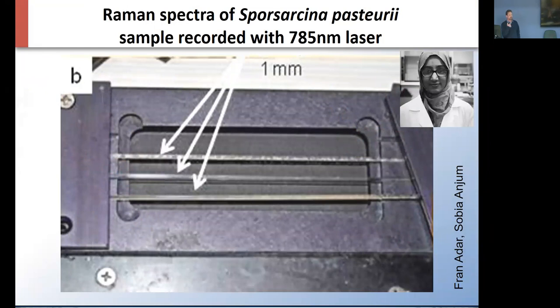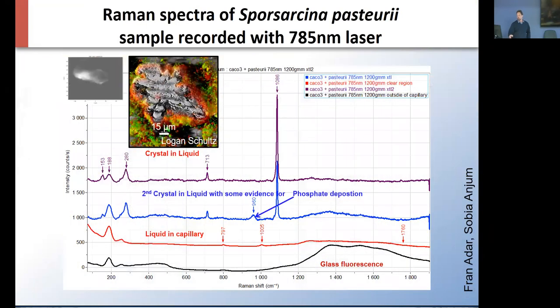So again, going back to what would happen in a flow system where we want to plug something, we use these capillaries, and Sobia, one of my PhD students, has worked with Fran Adar to basically, again, take these capillaries, and it's the same principle as I already explained in my previous slide with struvite. But what you see here is in the confocal, we can again image cells, red and green, as well as the crystal, but we don't know what it is. With the Raman scope, we can then go in and actually look at a crystal and get spectra. And again, there's glass, there's the liquid, and then we looked at two different crystals. One of them, or both of them, show us this 1086 peak, which is very characteristic for carbonates.